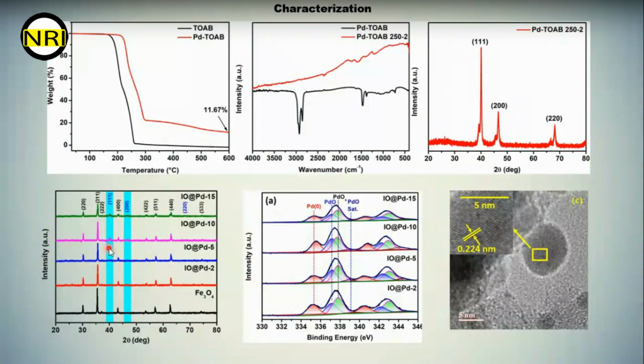The Miller indices written in black are due to the inverse spinel structure of Fe3O4, and the blue ones are due to the palladium nanoparticles. You cannot see the palladium peak for 2, 5 and 8% of palladium, because of the high dispersion of palladium over the Fe3O4, or maybe due to the narrow size of the palladium nanoparticles over the Fe3O4. But after increasing the palladium, we can see the palladium peak. So this may be the detection limit of XRD. We don't know, but mostly this is due to the high dispersion of palladium over the Fe3O4.